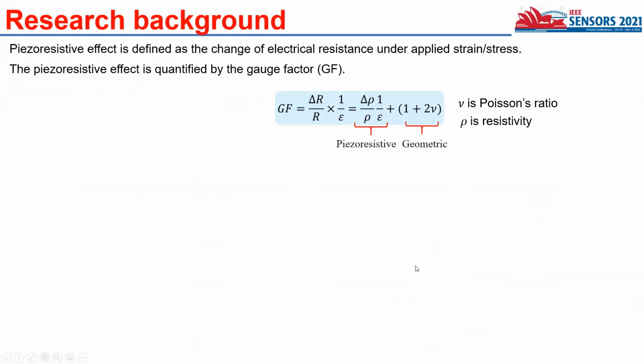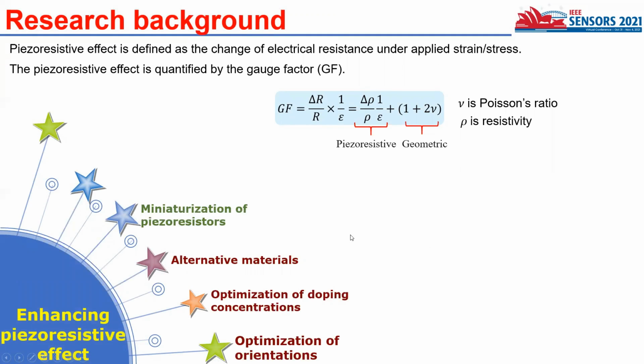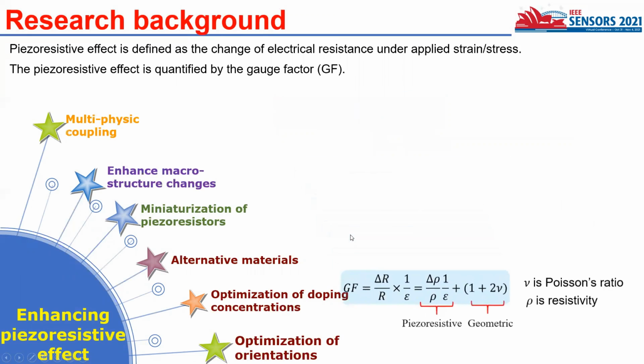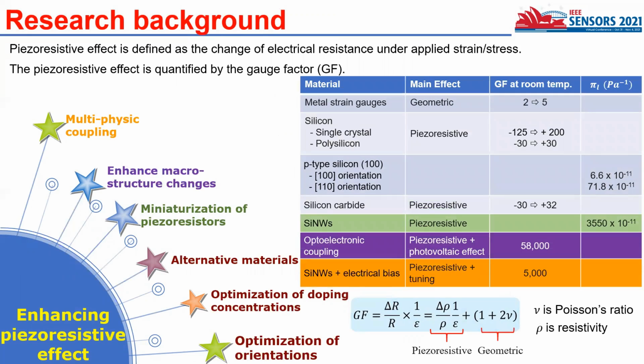The piezoresistive effect is defined as the change of electrical resistance under an applied strain state, and the piezoresistive effect is quantified by the gauge factor (GF), calculated as the equation on the slide. There are different ways to improve the performance of the strain sensor. For example, we can optimize the orientation of the piezoresistor, optimize the doping concentration, or use a material with a better piezoresistive effect. We can also scale down the size of the piezoresistor to the nanoscale.